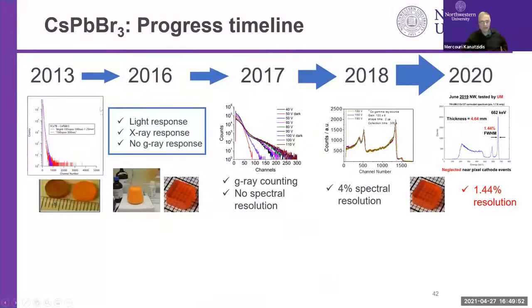So here's our progress. We identified this material in 2013. It was not very good. It couldn't respond to gamma rays. We improved the synthesis and the chemistry and the crystal growth. We got much higher quality material, but even that was not good enough to give us energy resolution in our gamma ray response. And at this point, I don't know if it was the material still not good enough or we were using a symmetric electrode. And so we had the wrong electrode. That's a mystery. But once we figured out the electrode, we were able to break it open and get spectral resolution as good as CZT on a one-to-one comparison, and then the pixelation.